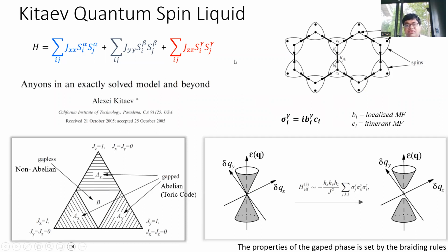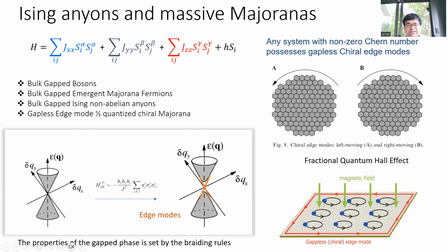And the way you get to those non-abelian excitations is by producing a very tiny magnetic field. What that magnetic field does at the level of perturbation is that in a gapless spin liquid, you get this gapless Majorana fermion band structure. But what a tiny magnetic field does is that it slowly starts to gap it out. And you can produce a band structure which is now slightly gapped by this magnetic field. And it's actually below this gap that you get these chiral edge modes.